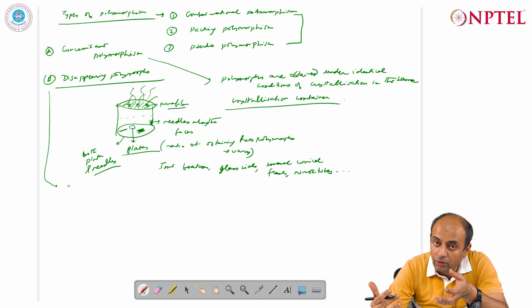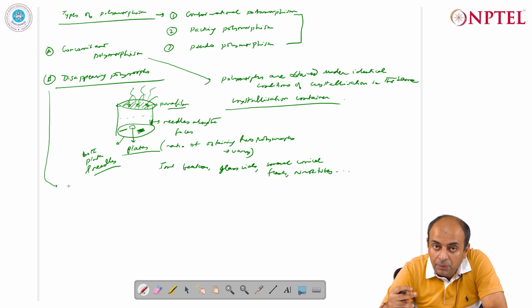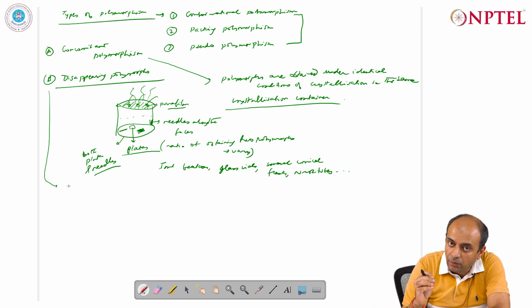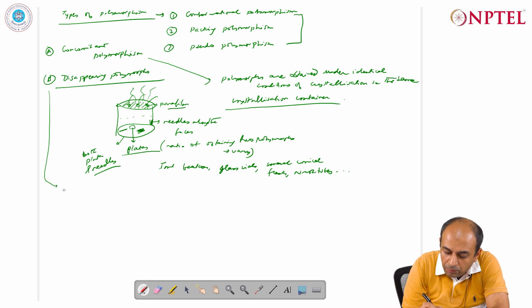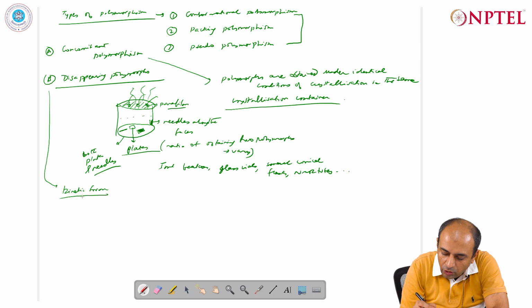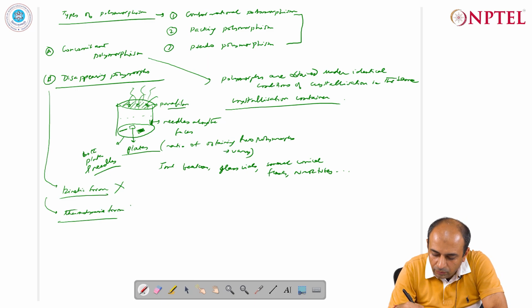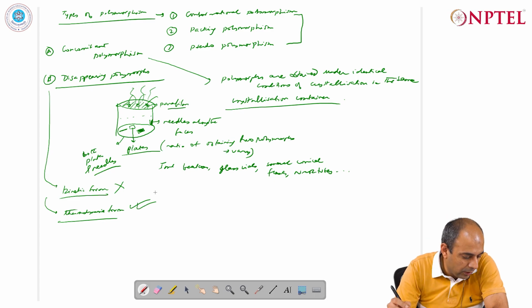So this is a very important exercise also in the pharmaceutical industry, that people would always like to reproduce the initially obtained form. The initially obtained form, which is no more crystallizing, is possibly the kinetic form, which would have been initially formed at a faster rate, but is now very difficult to control, and therefore what you are obtaining when you crystallize it regularly is the thermodynamic form. So you are not able to reproduce the kinetic form. Whenever you try to crystallize, you only get the thermodynamic form.